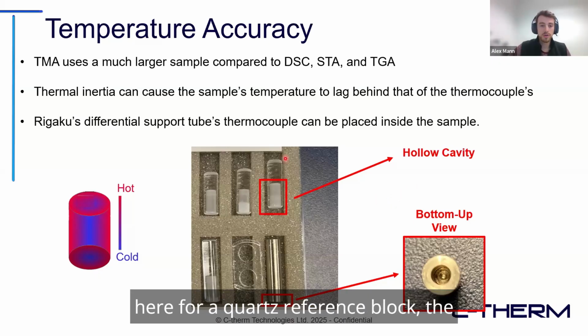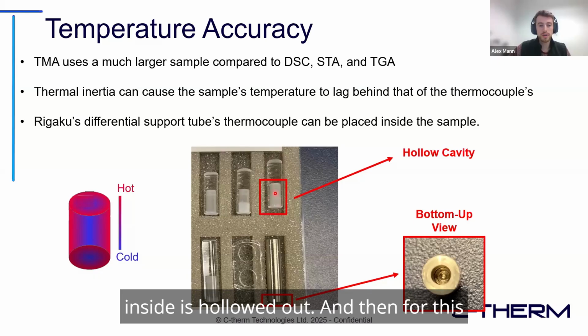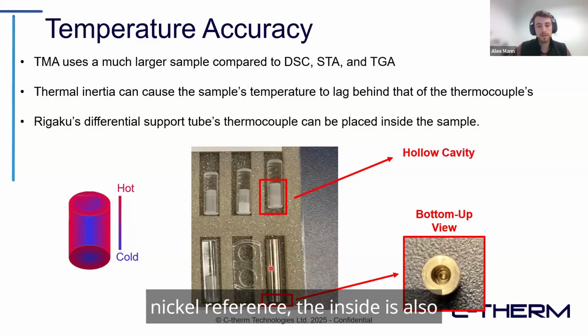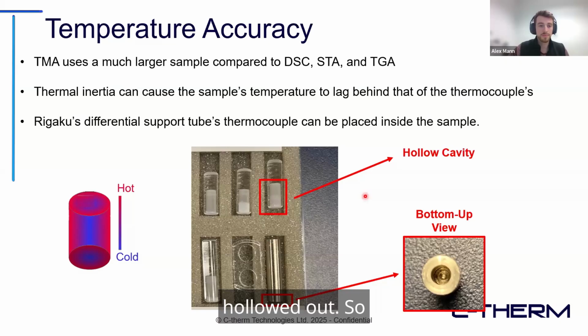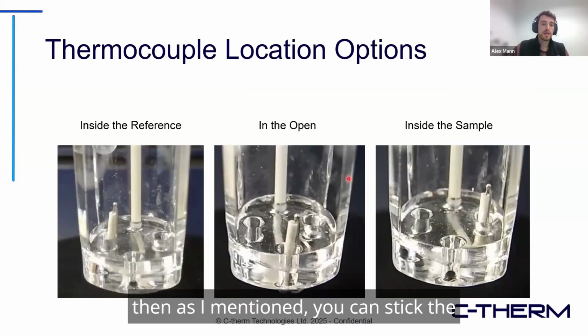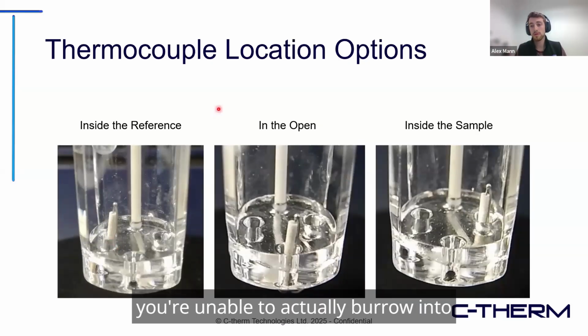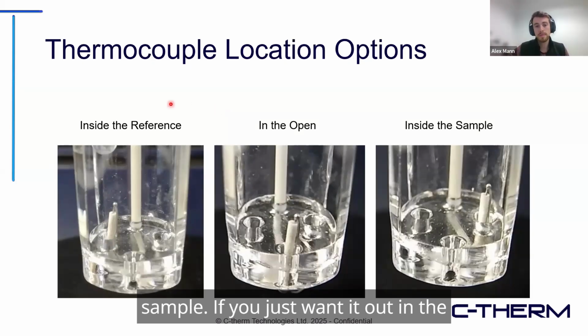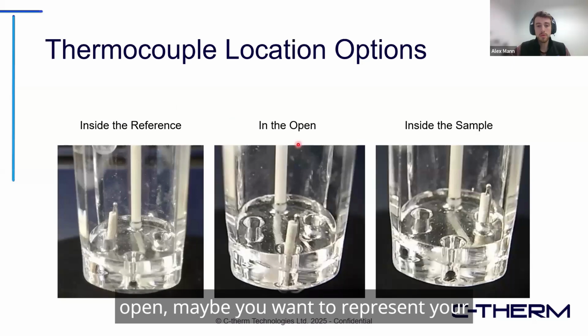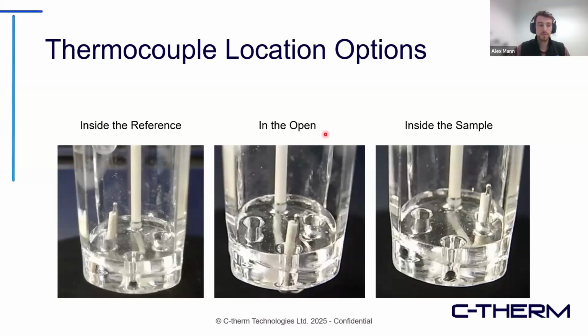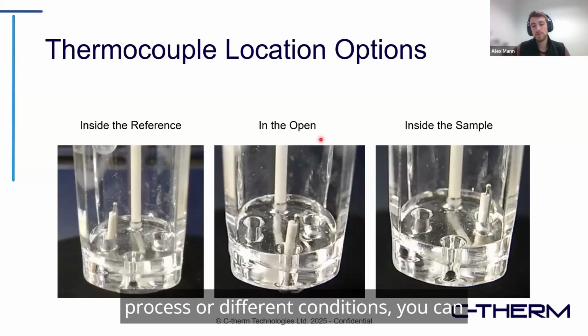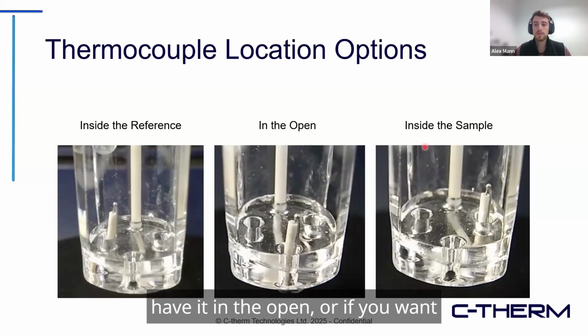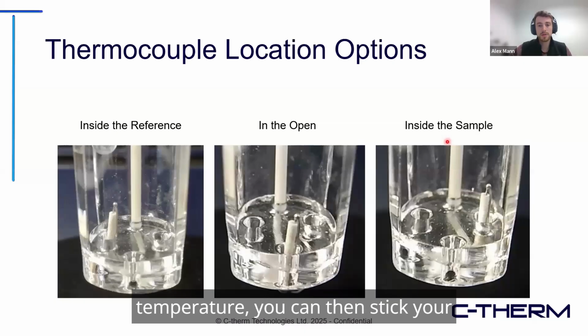So we can see here for a quartz reference block, the inside is hollowed out. And then for this nickel reference, the inside is also hollowed out. So then, as I mentioned, you can stick the thermocouple inside the reference. If you're unable to actually burrow into your sample, then you can use the reference sample to mimic your actual sample. If you just want it out in the open, maybe you want to represent your own process or different conditions, you can have it in the open. Or if you want the most accurate material property temperature, you can then stick your thermocouple inside the sample.